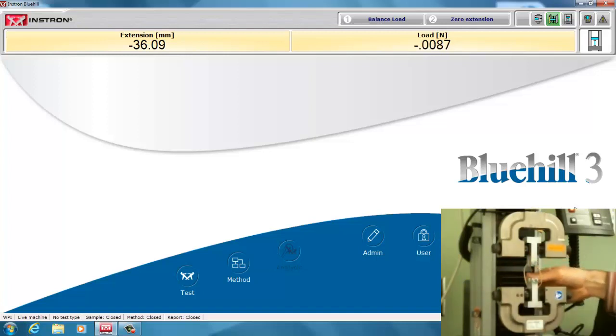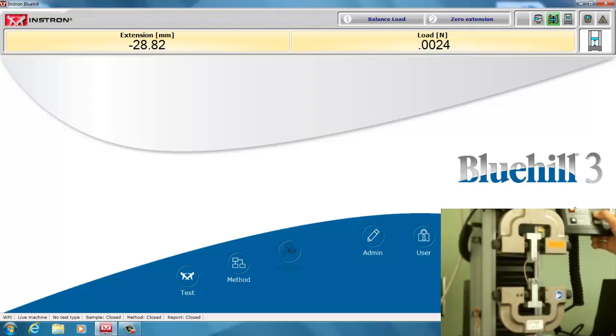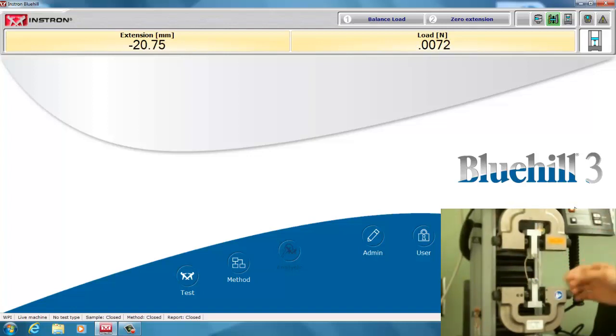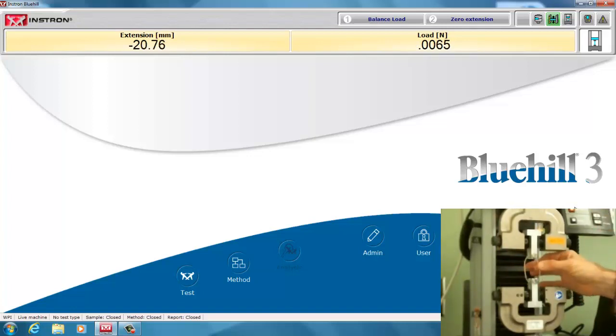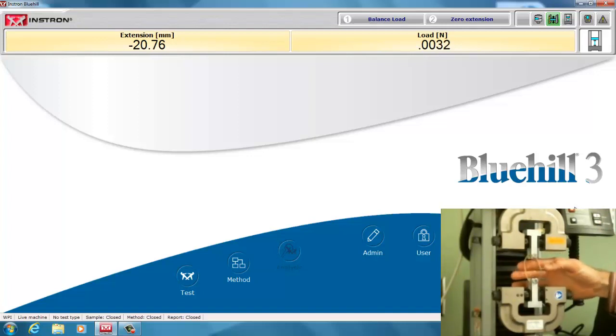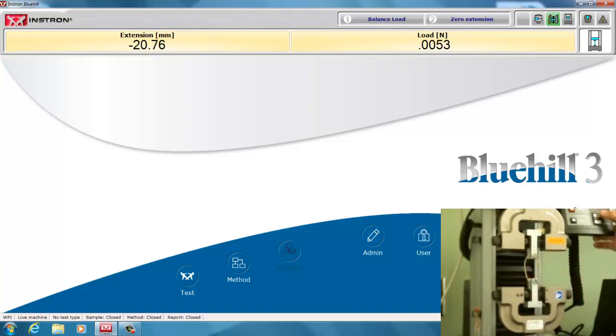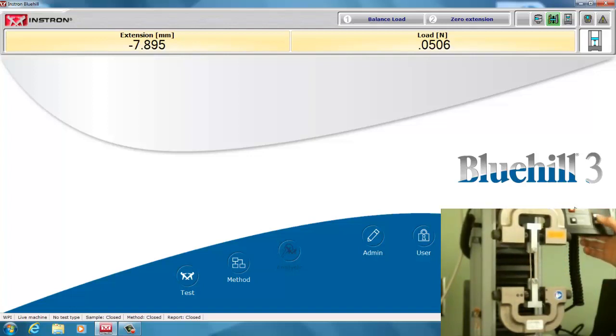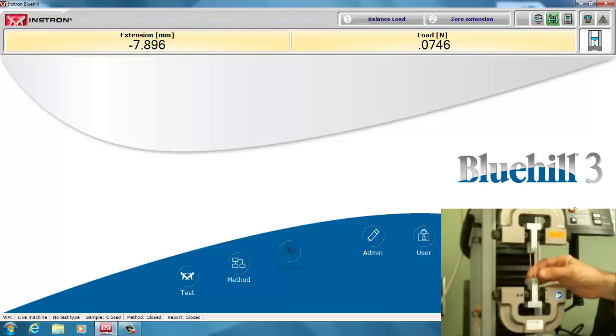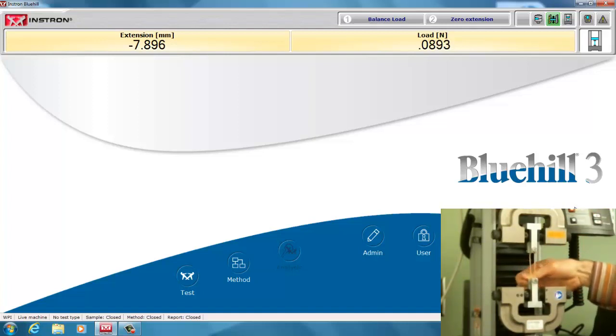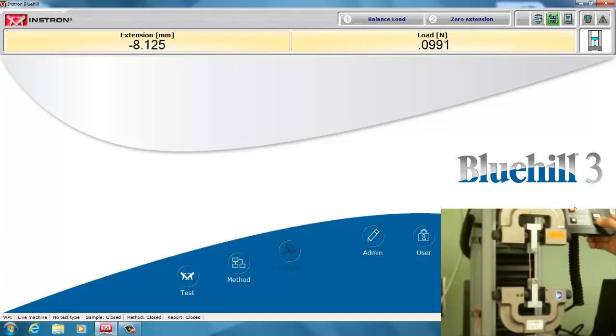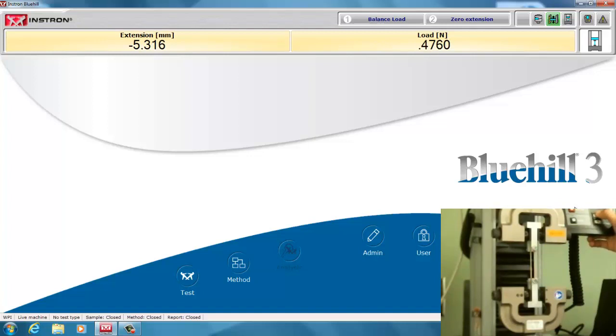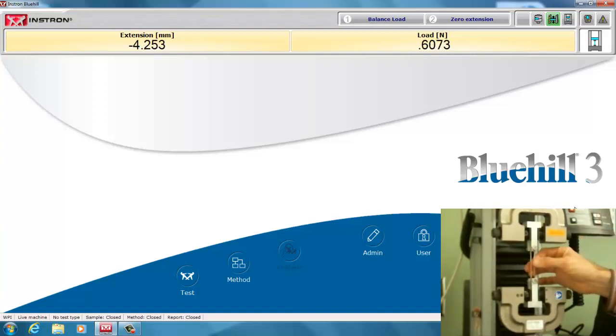You can use any kind of tensile test. Usually, I will put a tare load. This is a very small rubber band, so it's going to be hard to even get a nice tare load on it, but we want to make it essentially straight, and this machine has a 2,000 Newton load cell, which is a bit too high for this small of a sample. We could bring it up to half a Newton here below the accuracy of the load transducer.